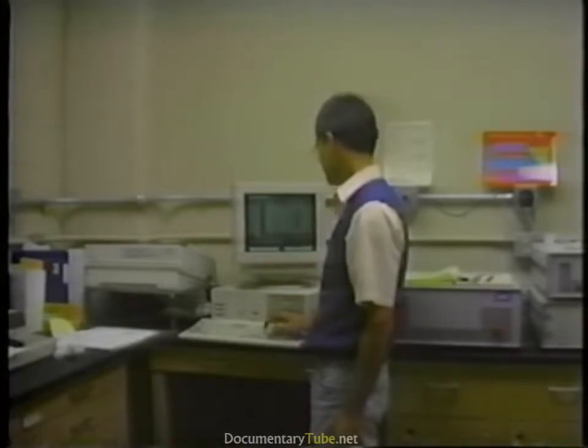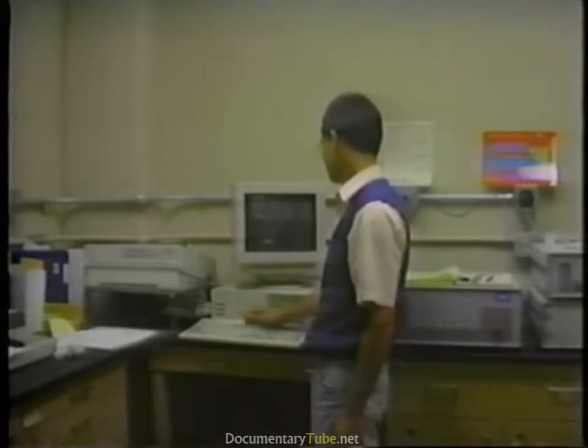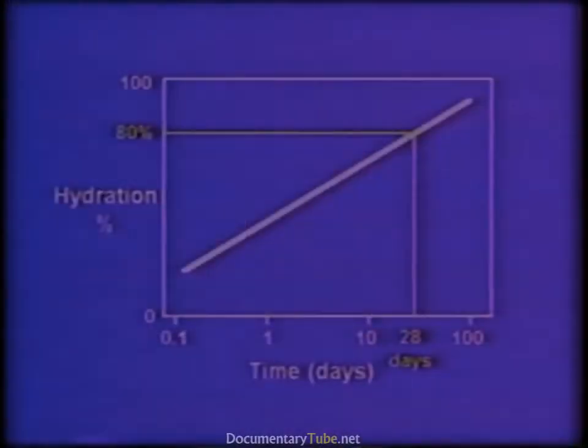The degree of hydration is calculated from the weight of chemically combined water. A typical cement paste cured in moist conditions will reach a degree of hydration of about 80% in 28 days.